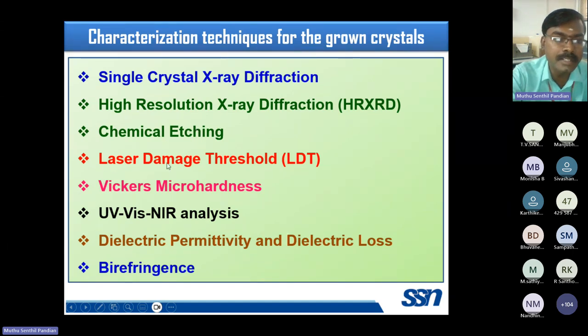We performed single and multi-shot laser damage threshold measurements to identify the laser damage threshold value of the grown crystal for laser applications. To check the mechanical stability of the SCST and SR method grown crystals, we selected Vickers microhardness measurement. For optical quality, UV-Vis-NIR. For electrical measurement, dielectric permittivity and dielectric loss. For optical homogeneity, we performed the birefringence measurement.